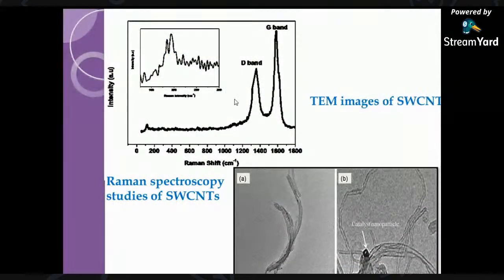So XRD, Raman spectroscopy will confirm the presence of single wall carbon nanotubes. Apart from the D band and G band, which are common bands generated in most carbon materials, when you come to a single wall carbon nanotube, you see an extra peak over here. It's called the radial breathing mode, and this represents the single wall carbon nanotubes. And these are the TEM images showing the formation of single wall carbon nanotubes coming from a nickel catalyst. And this follows a bottom growth mechanism of carbon nanotubes here. So it is very long, and it has a diameter of a few nanometers.